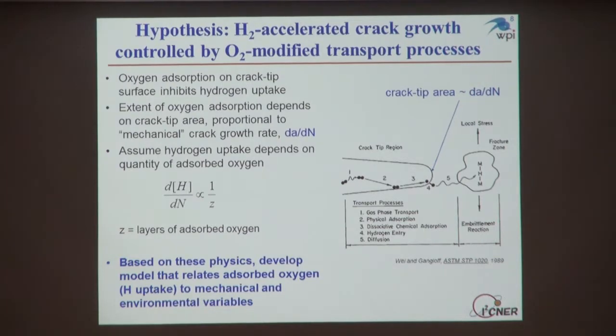So the more area we have, perhaps the less effective this oxygen adsorption would be. And this crack tip area is proportional to the mechanical crack growth rate, the crack growth rate that we might measure in air. And we're going to assume that the hydrogen uptake depends on the quantity of adsorbed oxygen, that they're inversely proportional. So the more oxygen we have on that surface, the less hydrogen uptake we're going to have through these transport processes. Based on these physics, we want to develop a model that relates the adsorbed oxygen, and by inference the hydrogen uptake, to the mechanical and environmental variables that we used in the experiments.